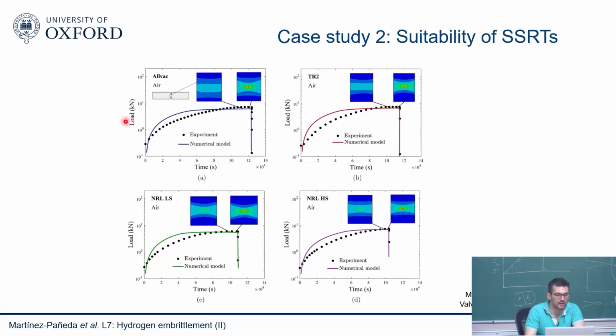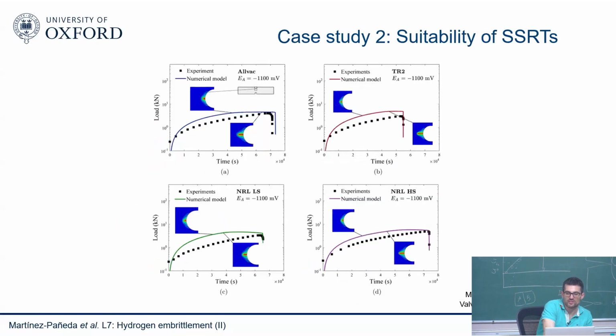So you can see this is the typical result you get in those experiments. You get load versus time, and basically you ramp up your load, and then eventually you get a drop in your load due to the failure. In this case, the failure happens in the center due to necking and so on, and this is in agreement with what we saw in the experiments. So phase field predicts failure happening in the center of the sample, and we seem to be in good agreement in terms of when things fail. This is with no hydrogen. The moment they bring hydrogen into the picture, they see failure happening at the edge, and we see exactly the same. As you can see, we get quite good agreement across the board.